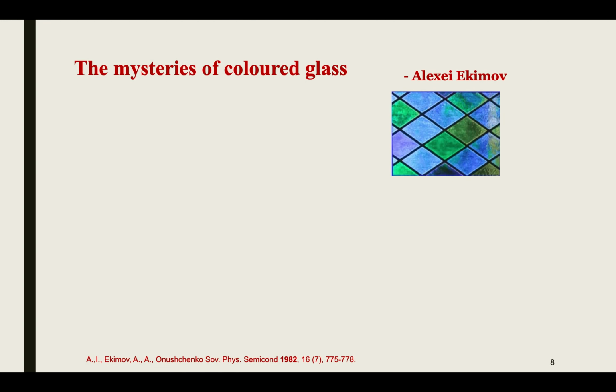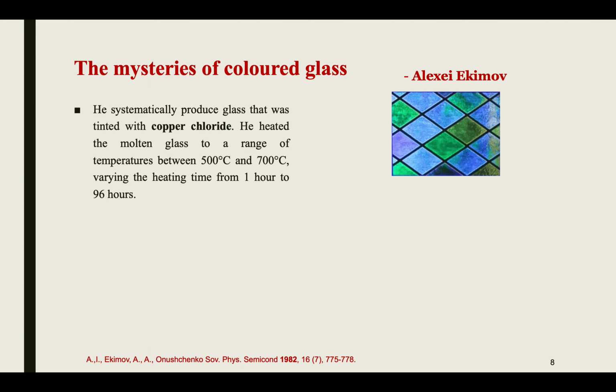So the mystery of colored glass was initially given by Alexei Ekimov. As you can see in this figure, he synthesized glass which has a different color. He systematically produced glass that was tinted with copper chloride. He heated the molten glass to a temperature between 500 degrees Celsius and 700 degrees Celsius, varying the heating time from 1 hour to 96 hours. He was working in the field of glass production, as well as tinted or colored glass. For the color, he used a metal salt, copper chloride.